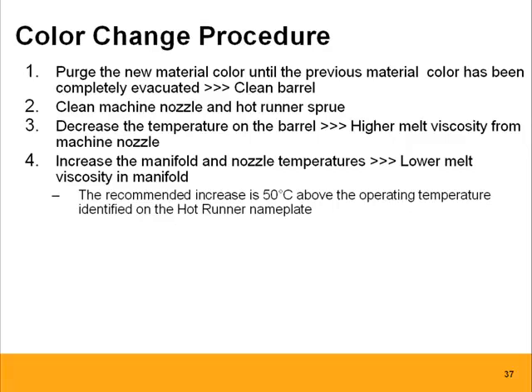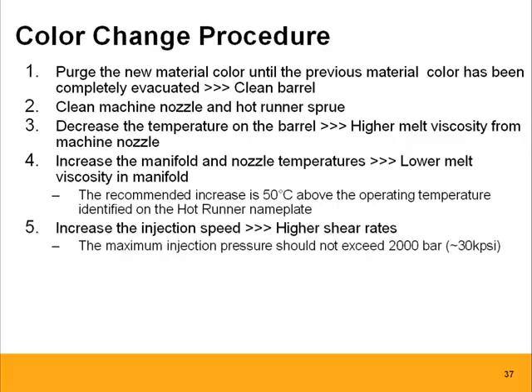The next thing that you can do in addition to that, what really helps, even if it's not really a scraping action, is that higher shear rates help change colors faster. So what we recommend is to increase the injection speed. You're not really concerned about making good parts, because the parts will be scrap anyway. You shouldn't, of course, exceed what your machine is capable of. You don't want to cause damage to the mold or the machine. But in general, we recommend increasing the injection speed during the color change process.